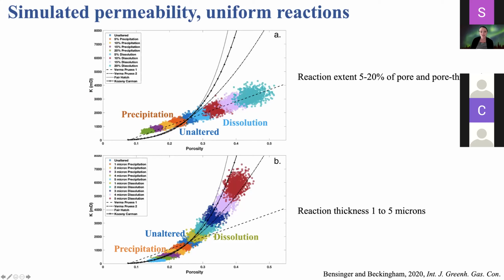We can then reflect dissolution occurring by increasing the pore and pore throat sizes, and precipitation by decreasing pore and pore throat sizes. On the top here, we have looked at uniform reactions occurring. Those are occurring on all pores and pore throats, and altering those pores and pore throats by an extent relative to their initial size. You can see that dissolution results in an increase in porosity and permeability, and precipitation results in a decrease in porosity and permeability. We also have those macroscopic porosity permeability equations I'm showing on these plots as the black lines.